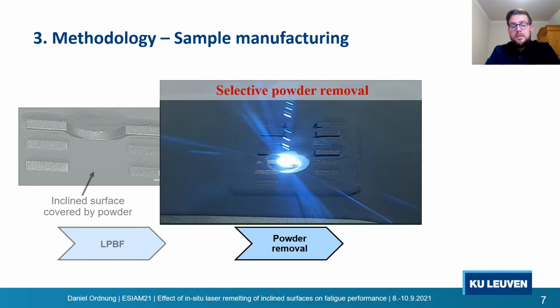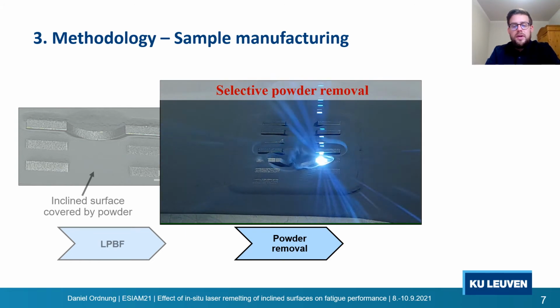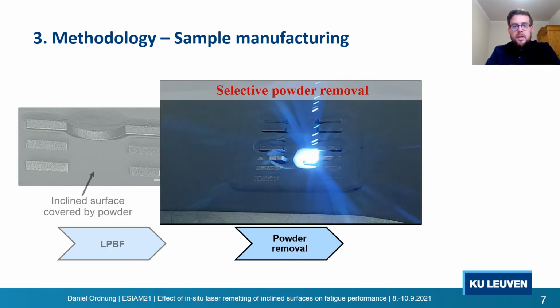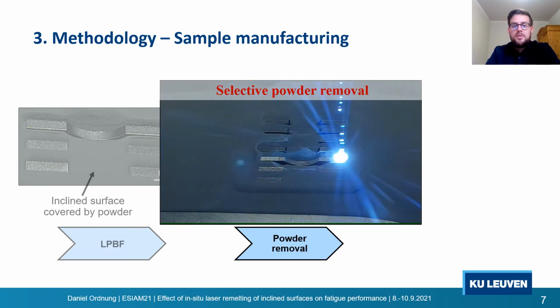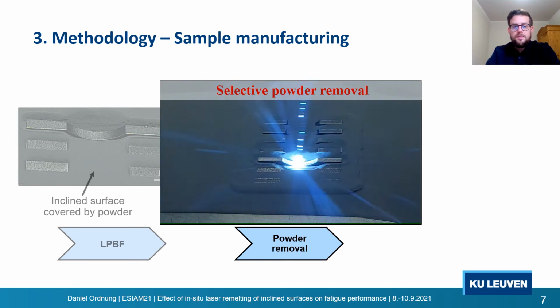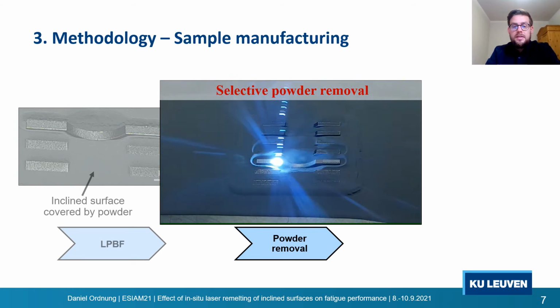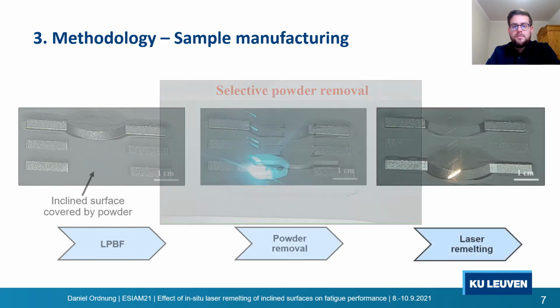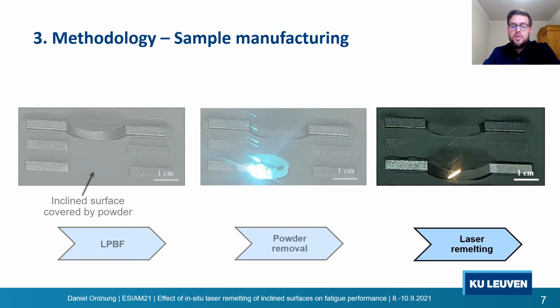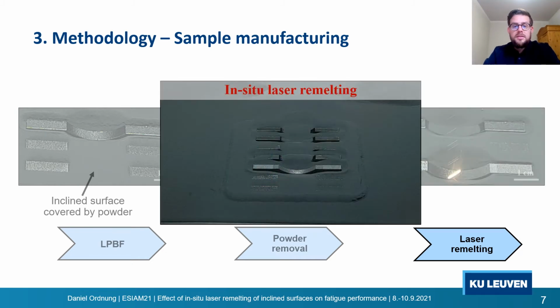We developed a special scanning strategy which allows to very efficiently clean inclined surfaces from powder. Here, this process is repeated incrementally until the laser reaches the bottom part of the inclined surface. At the end, the entire part surface is scanned again by the pulsed wave laser to get rid of last powder particles. And as you can see, the entire surface is clean of powder. And thus it is now possible to actually access it with the continuous wave laser to laser remelt the surface.